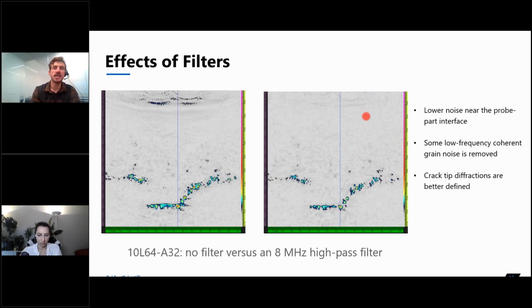One thing that we have found is actually very effective for reducing that coherent noise is the use of a filter. So in general, applying an 8 megahertz high pass filter, or whatever is just below the frequency of our probe, is very effective at cutting out a lot of that coherent noise that we can see in certain images.